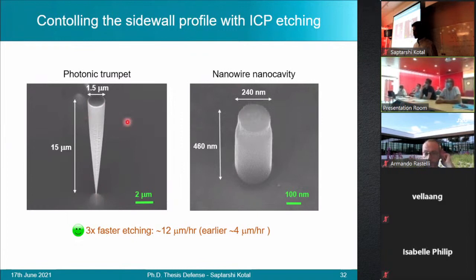This process relies predominantly on a chemical etching process, which allows to define these undercut angles. By the end of our optimization of the recipe, we were able to obtain a routine that allowed to etch tall samples 3 times faster than what was achieved in the team in the past. This is highly desirable for etching tall samples like these.